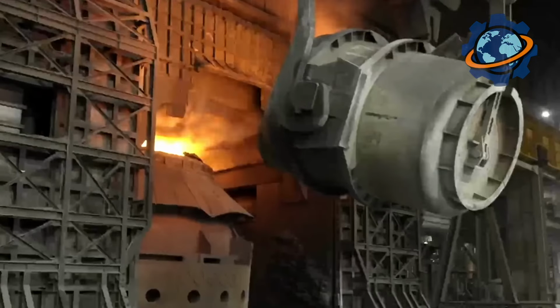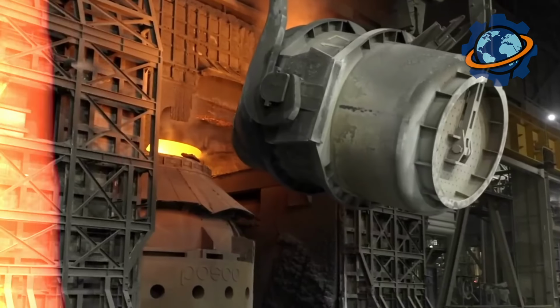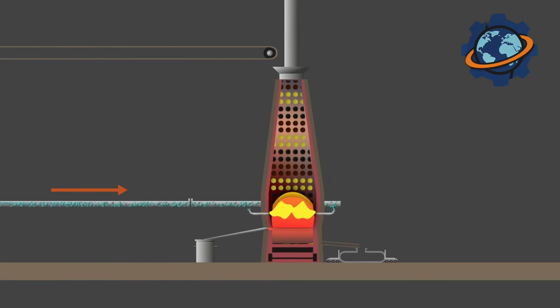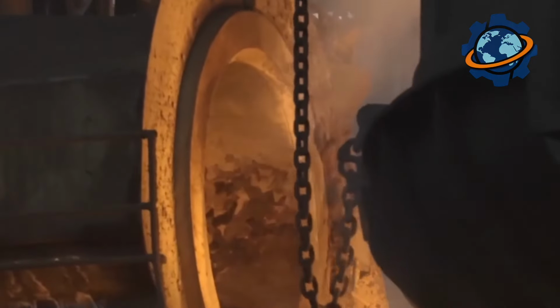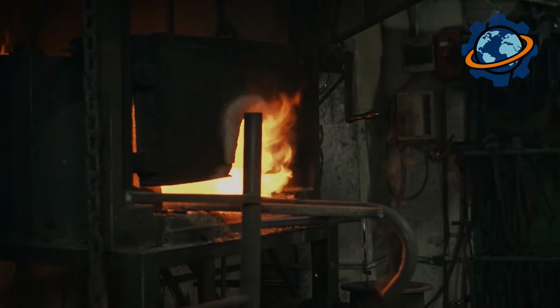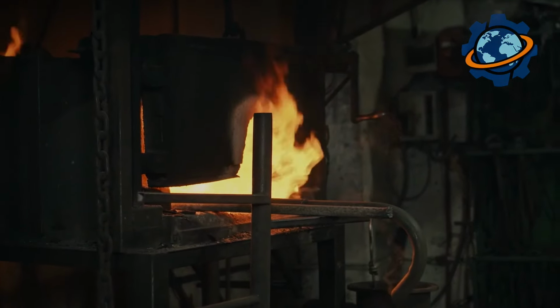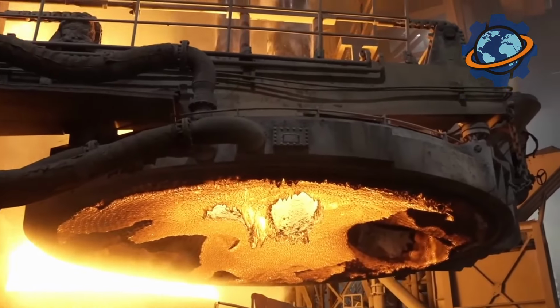Metal boils and churns. Flame tongues several feet high shoot from the converter mouth, sparks and molten drops fly everywhere. The blowing process takes 20 minutes. In this time, 350 tons of pig iron become steel, with carbon burning down to 1% or less.